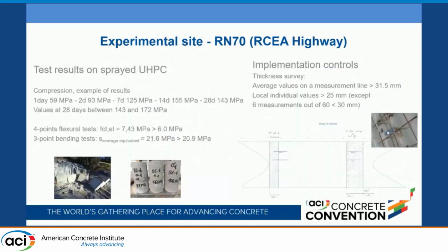The test result validated the mechanical characteristics. A compressive strength higher than 50 MPa at 1 day and 140 MPa at 28 days can be noted. The verification of the fiber dosage has given adequate results. Further investigations were carried out on the actual thickness applied.